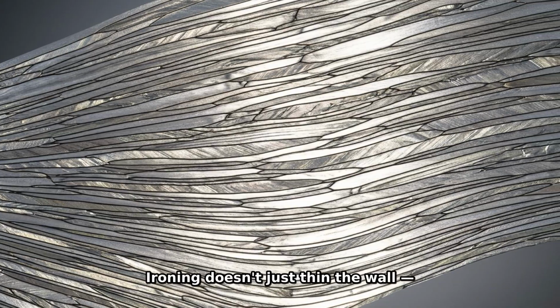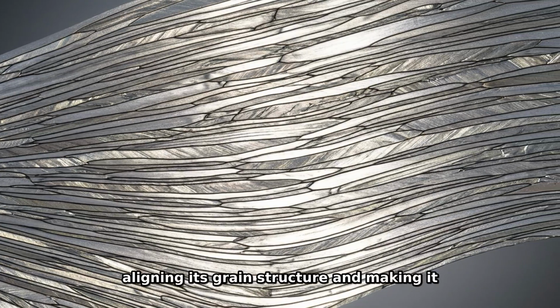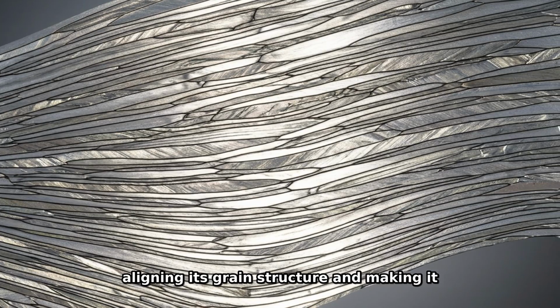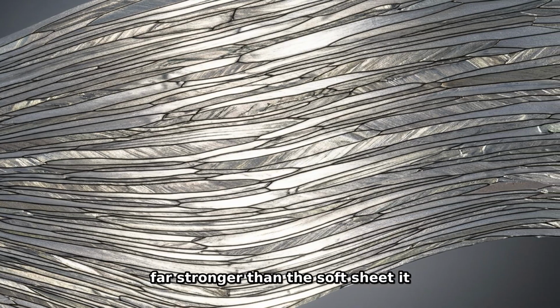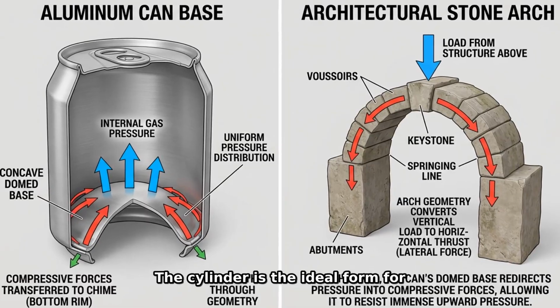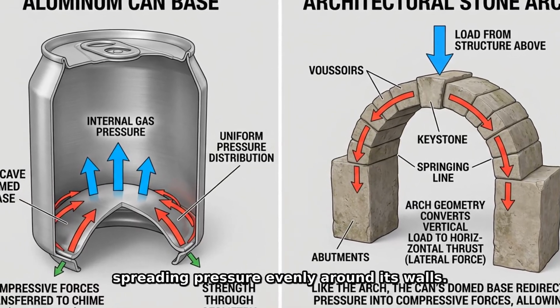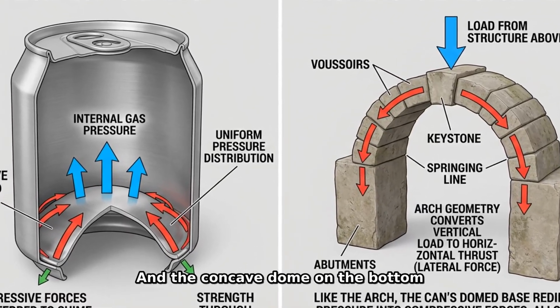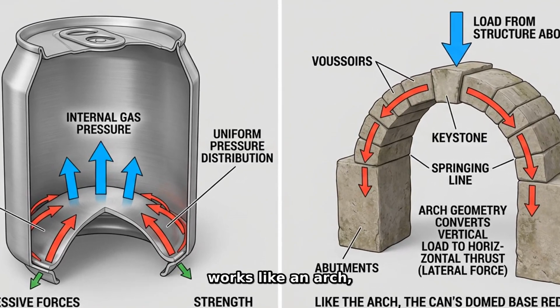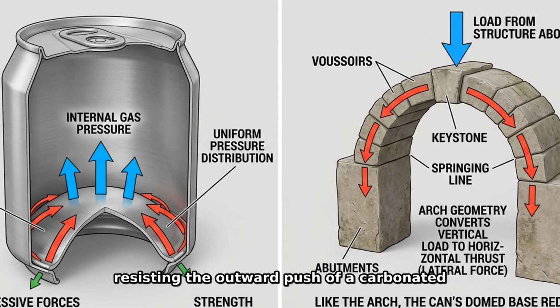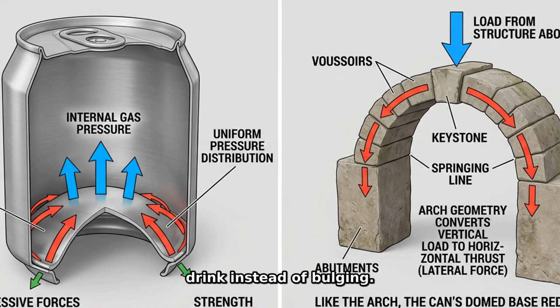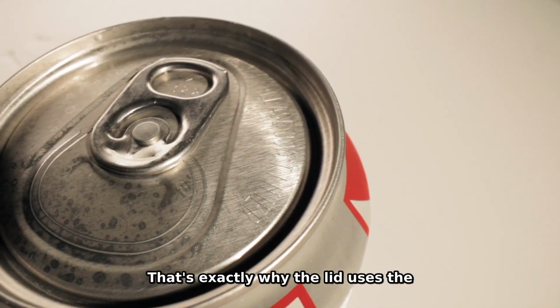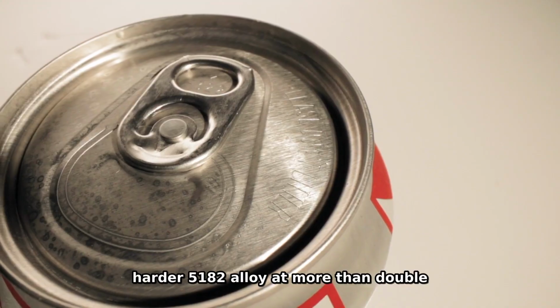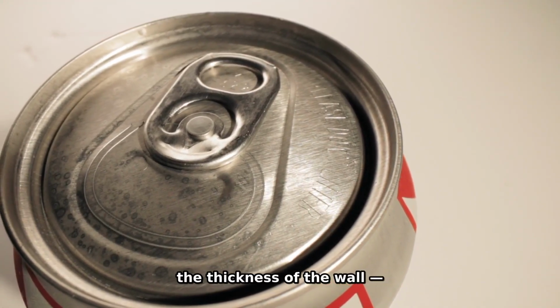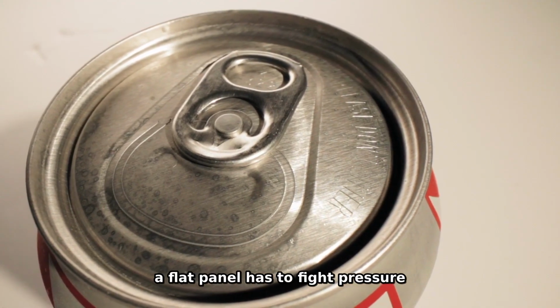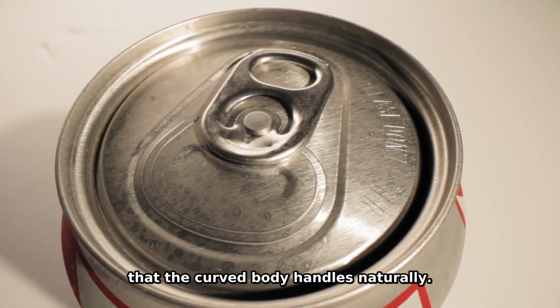Ironing doesn't just thin the wall, it work hardens the aluminum, aligning its grain structure and making it far stronger than the soft sheet it started as. The cylinder is the ideal form for spreading pressure evenly around its walls, and the concave dome on the bottom works like an arch, resisting the outward push of a carbonated drink instead of bulging. That's exactly why the lid uses the harder 5182 alloy at more than double the thickness of the wall. A flat panel has to fight pressure that the curved body handles naturally.